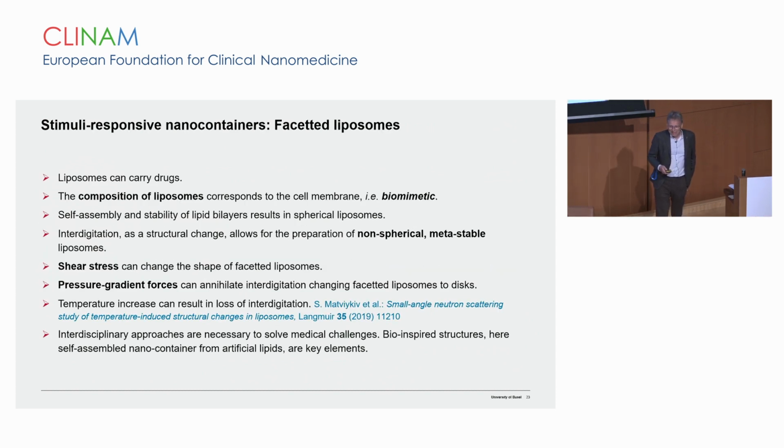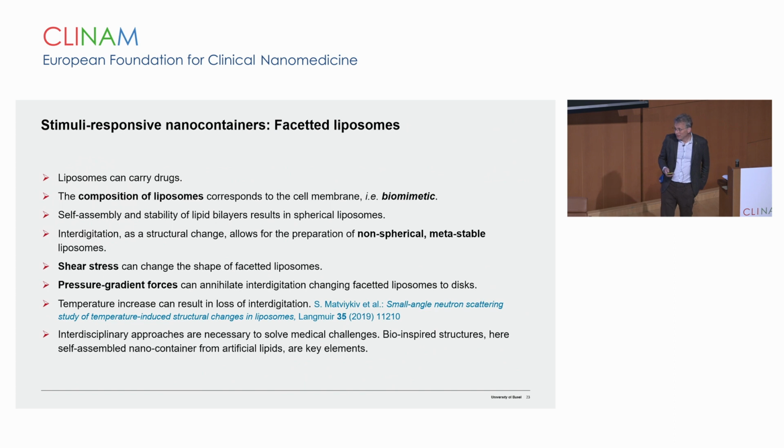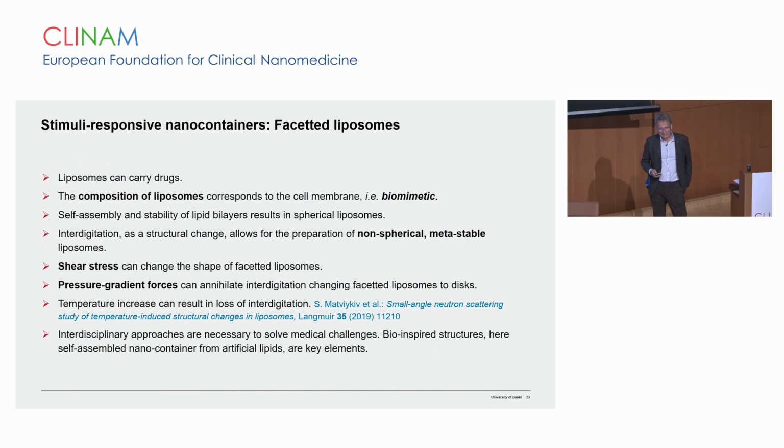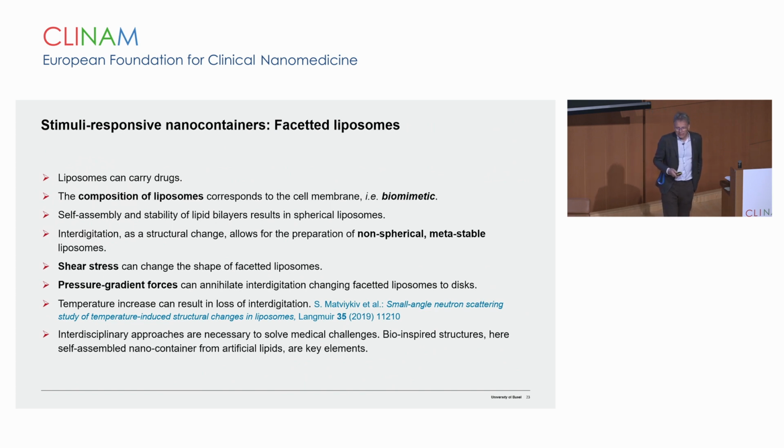With that, I would like to summarize my talk. So liposomes can carry drugs. That is very well known from many researchers, also presented at this conference. The composition of liposomes corresponds to something like the cell membrane, so it's biomimetic. Self-assembly and stability of lipid bilayers result usually in spherical liposomes, but interdigitation as a structural change allows for the preparation of non-spherical metastable liposomes with tailored properties. And shear stress can change the shape of the faceted liposomes, as was demonstrated experimentally.